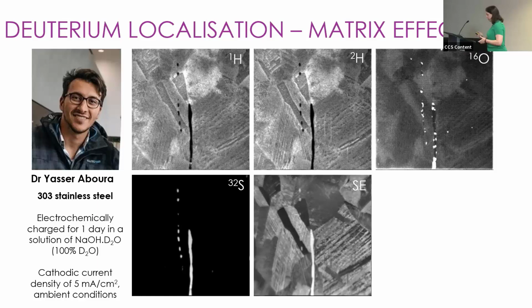So just an example of the first issue that we had to overcome with the NanoSIMS is something called the matrix effect. Here we have a series of images from the NanoSIMS: hydrogen, deuterium, oxygen, sulfur, which as expected shows a lot of sulfur in the manganese sulfides, and the secondary electron image, which was generated by the NanoSIMS. If we look at our hydrogen and deuterium maps, we can see in this region here, this particular grain seems to show a lot of hydrogen localized to it. Okay, so we think, why has that particular grain got more hydrogen than, say, this one, for example?